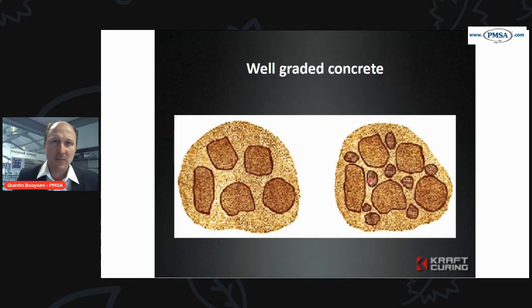You want that because you want your cement to be able to cover more particles or more aggregate. And when you have a lot of fine material in concrete, your cement has to work so much harder. It has to be spread over so much greater area, over every little particle, to generate strength. So when you have larger particles and well graded, the cement has a greater chance of creating a stronger concrete in the end.